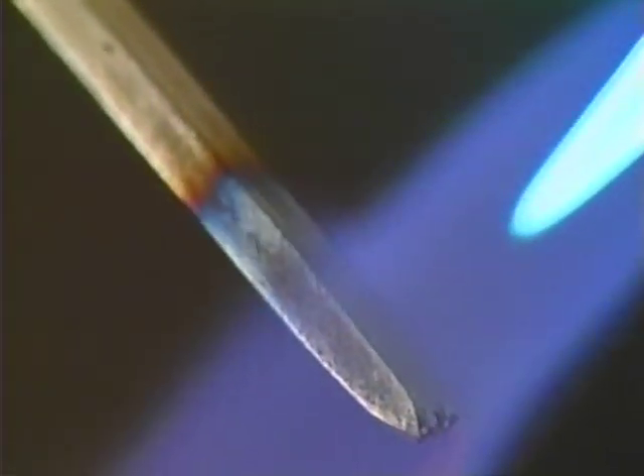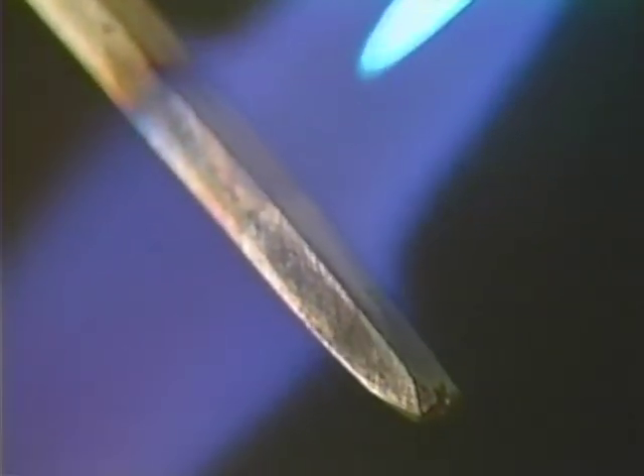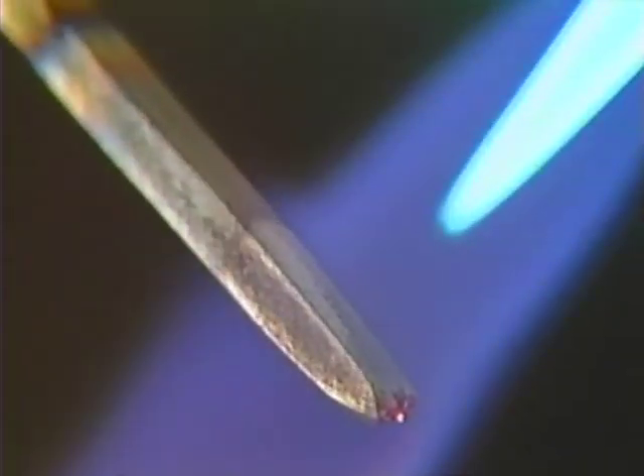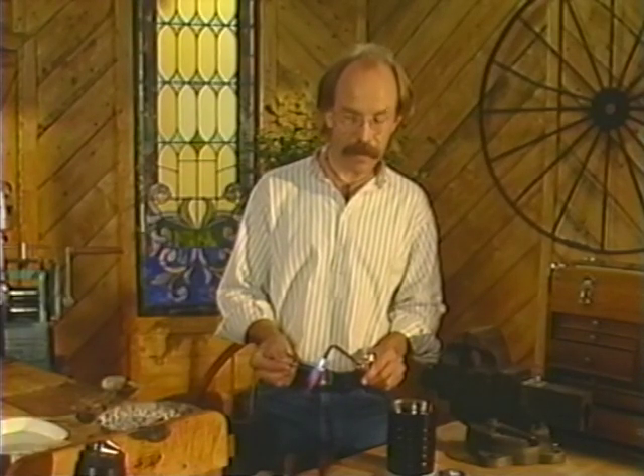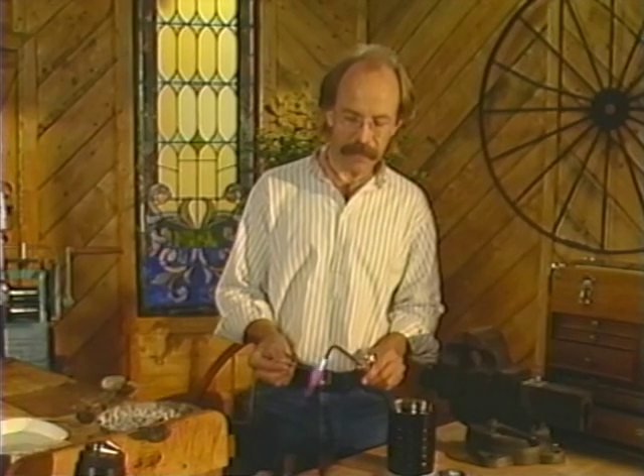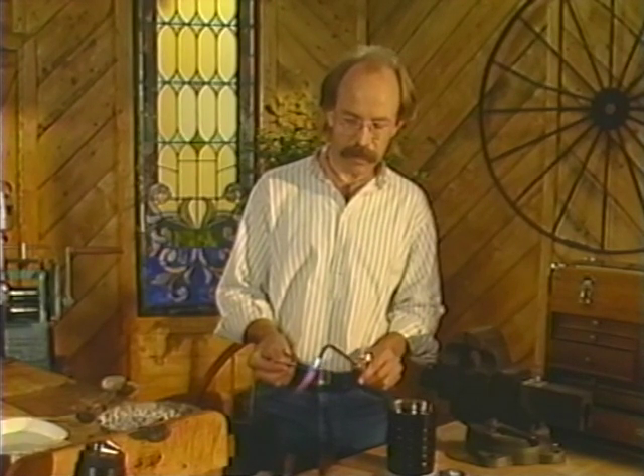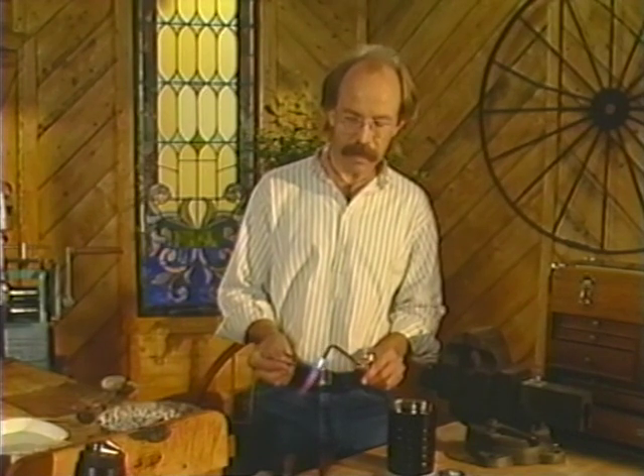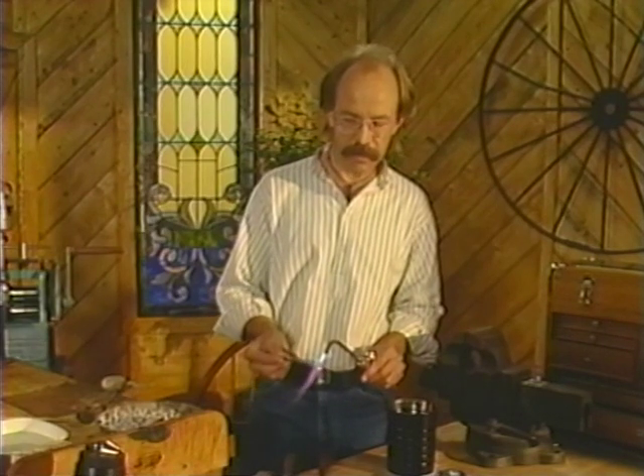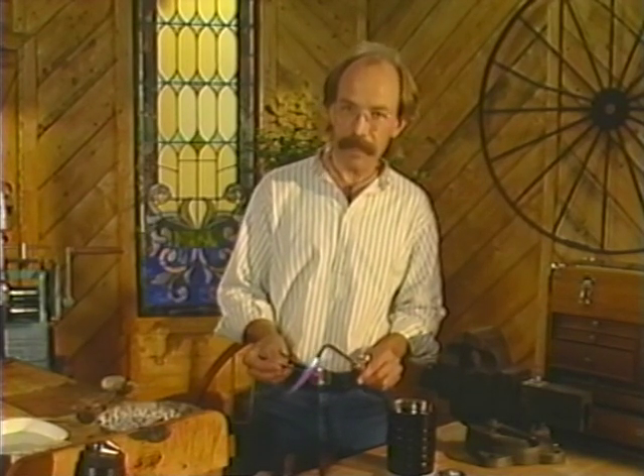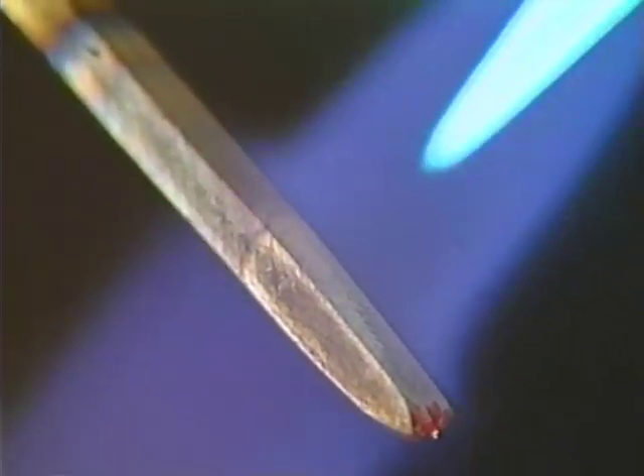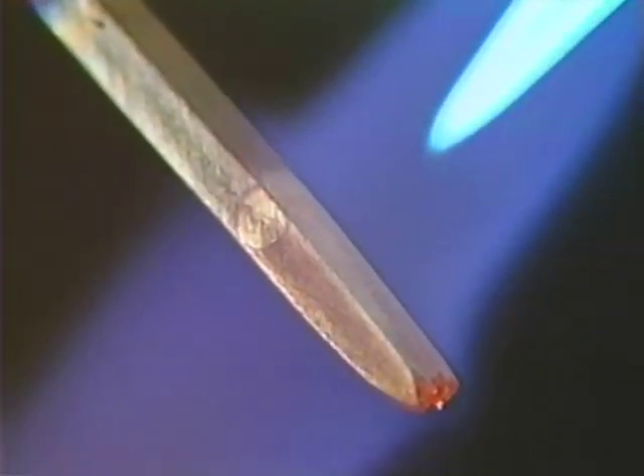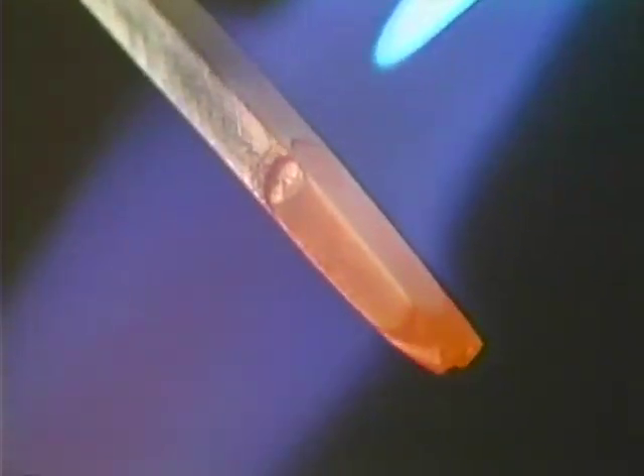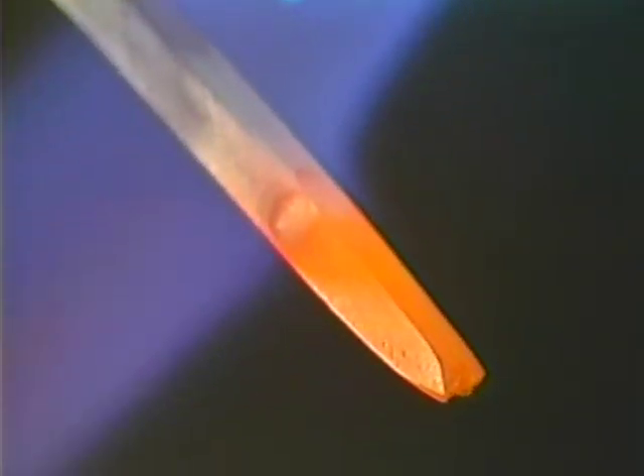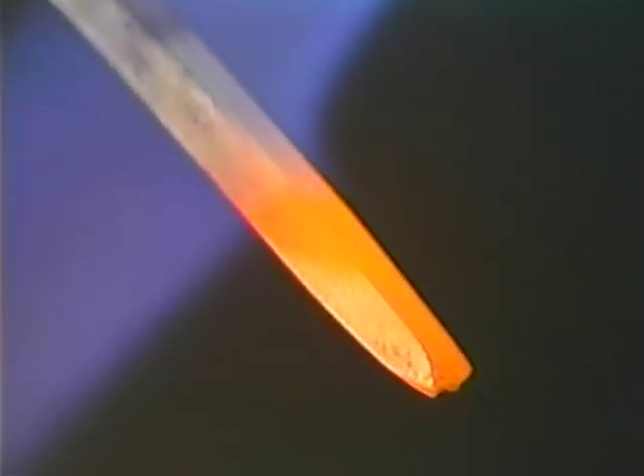My indicator is color. I'll be heating until it's a bright, luminous red. Another indicator, if you're not confident about reading color, is the fact that the steel, when it goes through that phase change, loses its magnetism. So you can keep a magnet close at hand and just touch the tool to it. And if it does not pick up the magnet, you'll know it's at the right temperature. That's approaching the right color. And now I'm going to very quickly move over to the oil and stir with the tool.